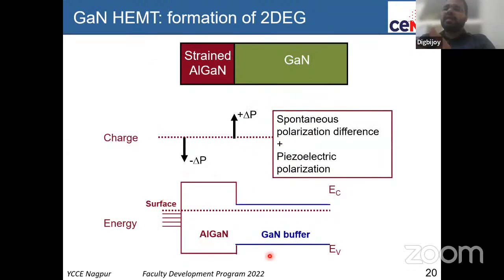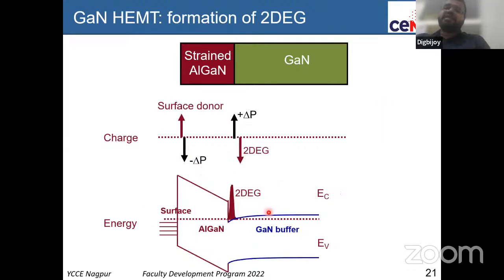There's a wider band gap aluminum gallium nitride, there's a smaller band gap gallium nitride. Gallium nitride is also wide, but aluminum gallium nitride is even far wider. So that's why the band diagram looks like this. Now there are two sheets of positive and negative charge at the interface, so the bands will bend. Why? Because there's an electric field. And because of the electric field, the band diagram eventually looks like this.